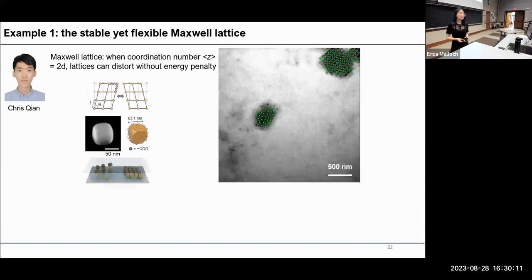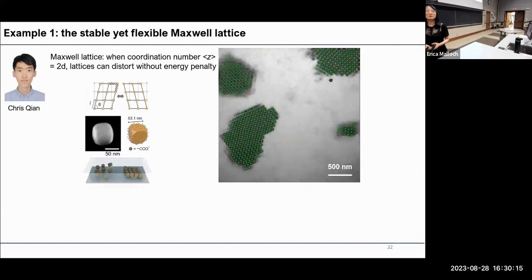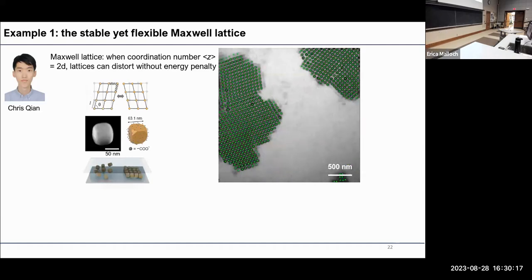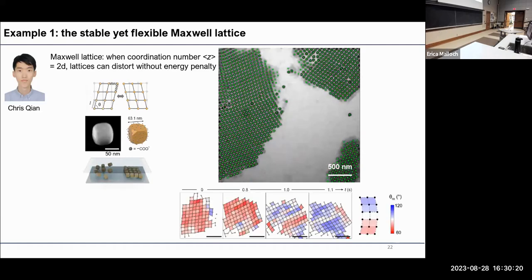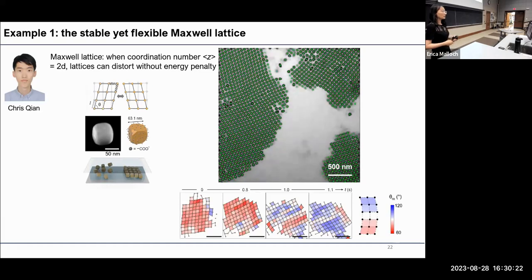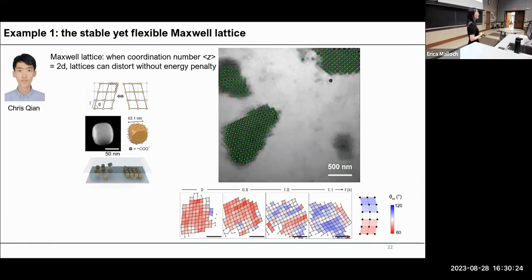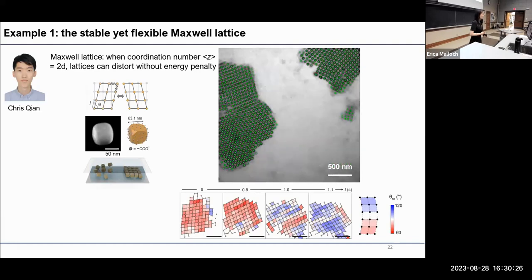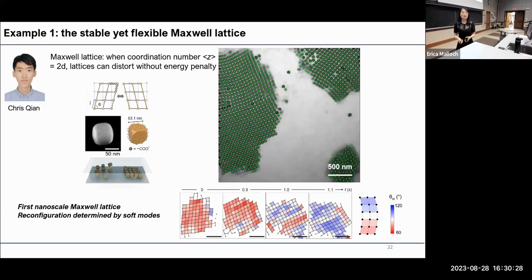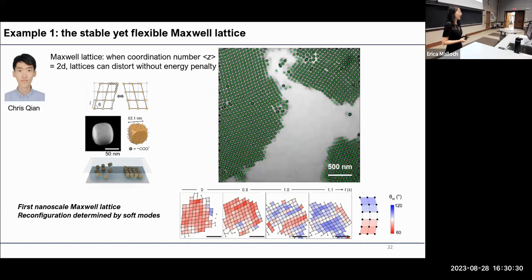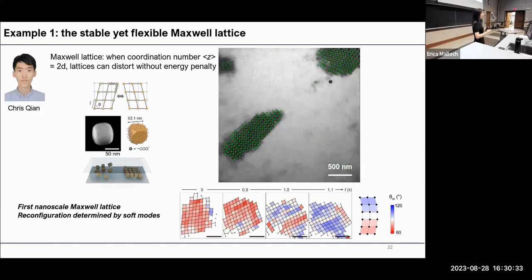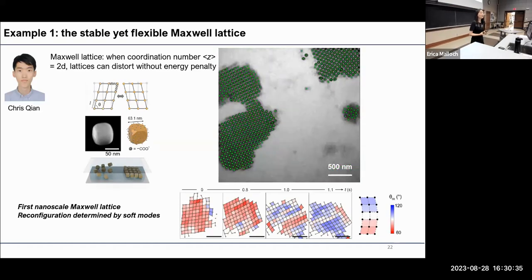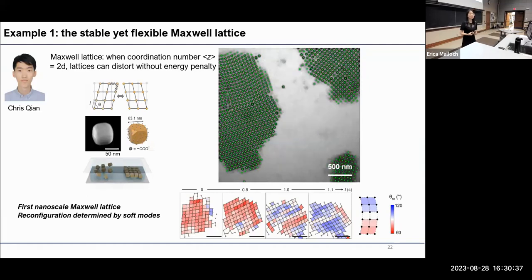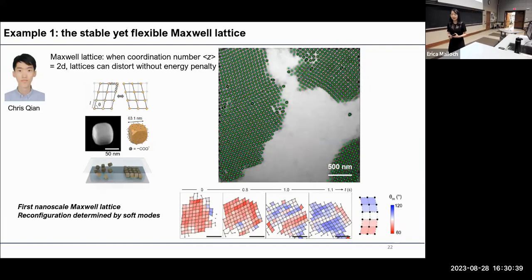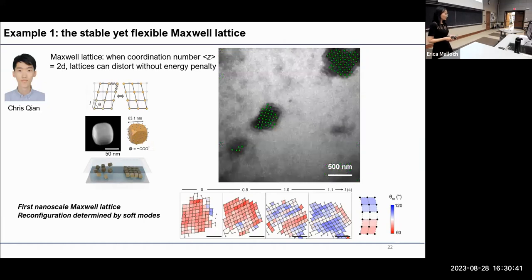So my student Chris was able to achieve this rhombic lattice from the self-assembly of gold nanocubes shown in this liquid phase TEM movie here. You can see the lattice actually undergo a lot of collective lattice rearrangement. I should mention this is actually the first nanoscale Maxwell lattice in action, and the large scale realization you're seeing is essentially a linear combination of soft phonon modes, which are characteristic of Maxwell lattices.